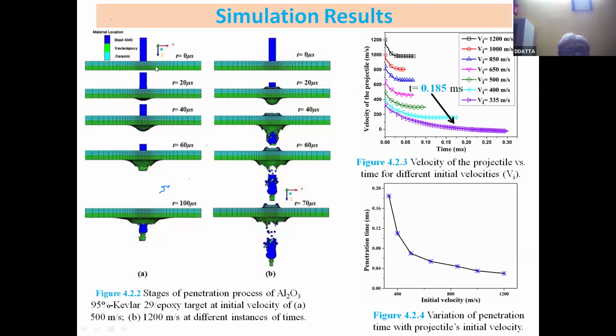Okay. So there are two things in the domain. One part is the ceramic part, that is the first part where the projectile first confronts. Here it is a brittle material. So the concept of brittle material is that it absorbs a lot of impact energy and gets fractured. So brittle fracture. Then it comes to the Kevlar epoxy. The Kevlar epoxy is a mixed filling. So we can also get to see the shear plug formation. The shear plug formation takes place by bulge at the back end. This is visible.